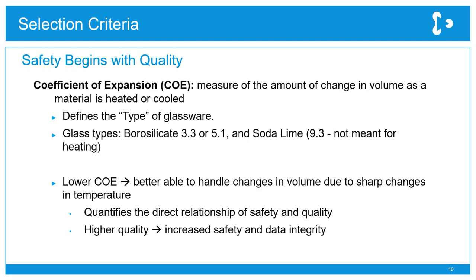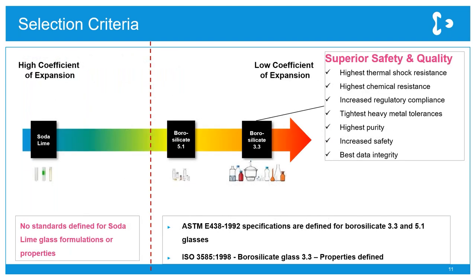It's also a very important consideration for the safe use of glass in labs: the coefficient of expansion. This is how much the material changes in volume when it's heated or cooled. The lower this is, the safer the material is, as it will stand up to much higher temperature changes. And here you can see that soda lime has a relatively high COE, typically 9, compared to the borosilicates.